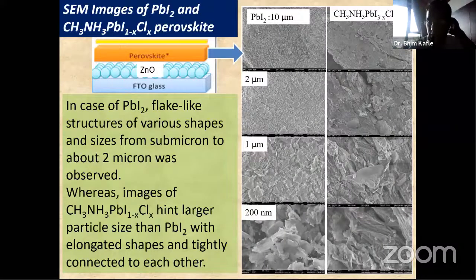Here we tested the crystallinity of only lead iodide. You can see very small particles here. After putting the methyl ammonium iodide, these rocky structures with very large particle size show a clear difference between lead iodide alone and with methyl ammonium iodide, which confirms one indication of the formation of the perovskite.